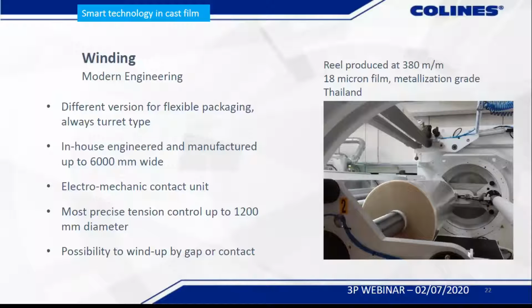One of the most important things is our electromechanical unit that permits us to work by gap or by contact, and I'm saying also the very soft contact, basically with no air entrapment, even for very thin film. The picture shows an 18 micron film for metallization produced for a very big multinational in Thailand at 380 meter per minute. And the maximum winding diameter is 1.2 meter.